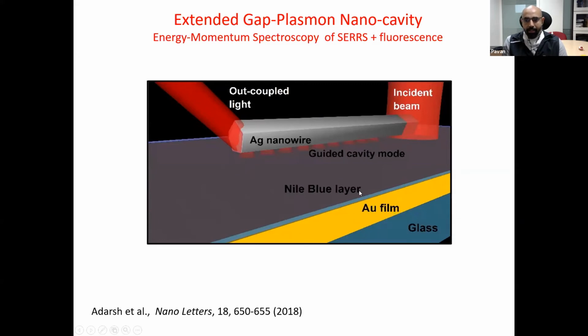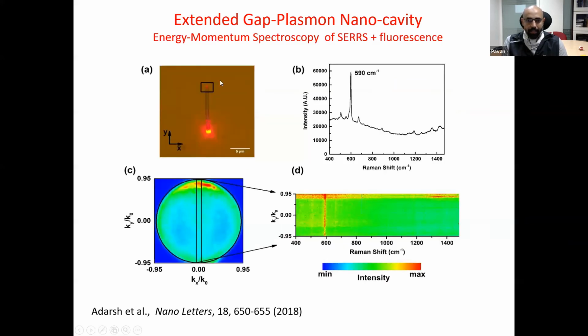Now, what is the consequence? The consequence is that you can now study remote excitation configurations, where you can incident light at one location and look at the light which is coming at a remote location. Shown here is a bright field image overlaid with the optical excitation image. Here you have the plasmon excitation from a 633 nanometer laser. You will see that the light is emanating from the distal end of the wire in the geometry.